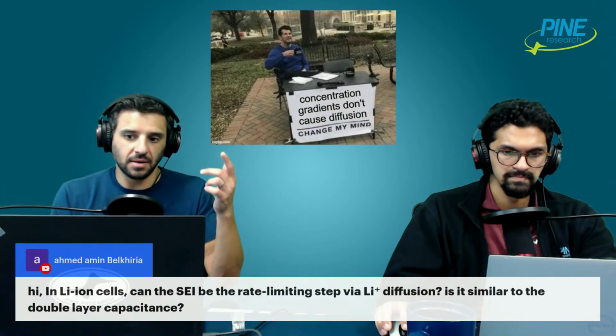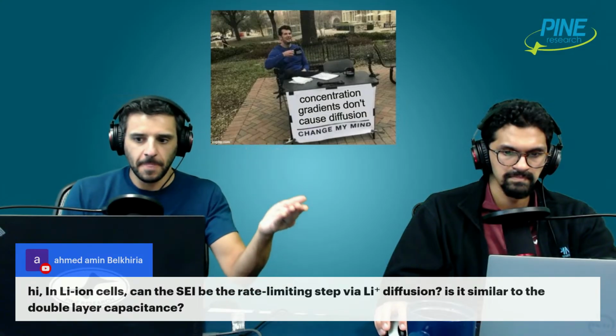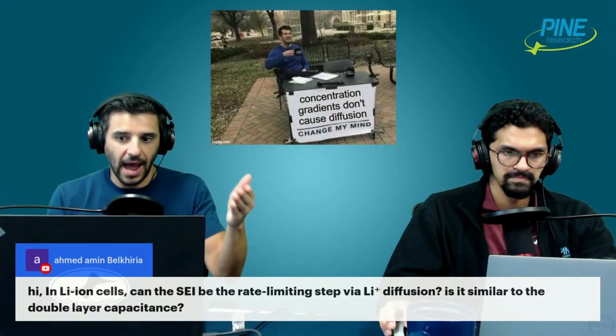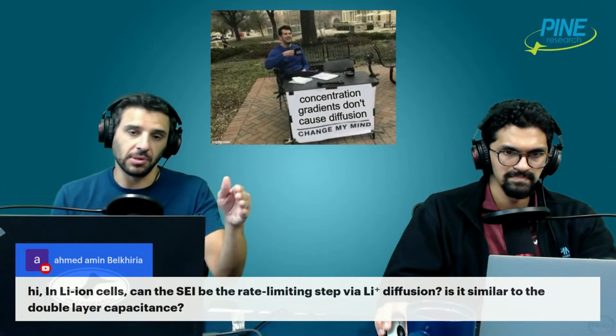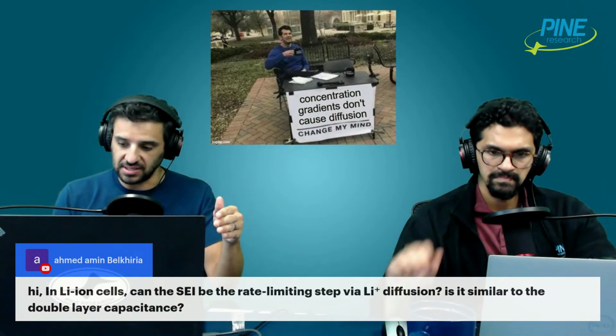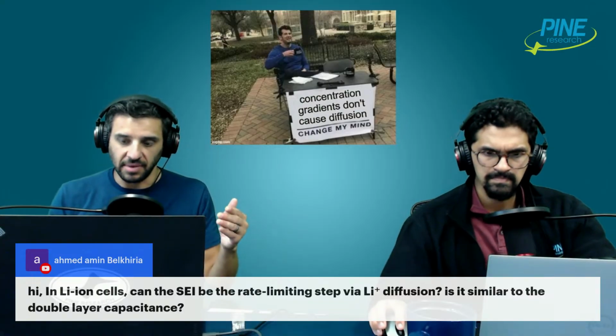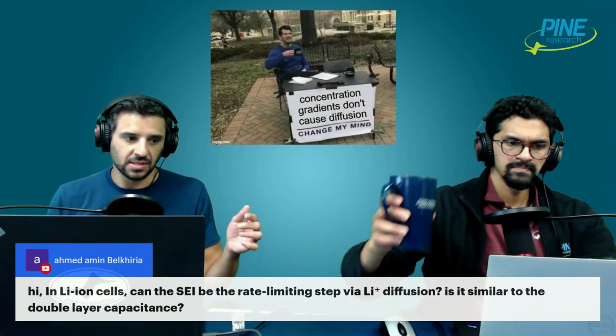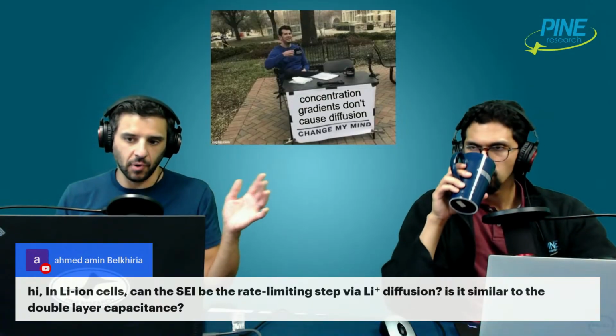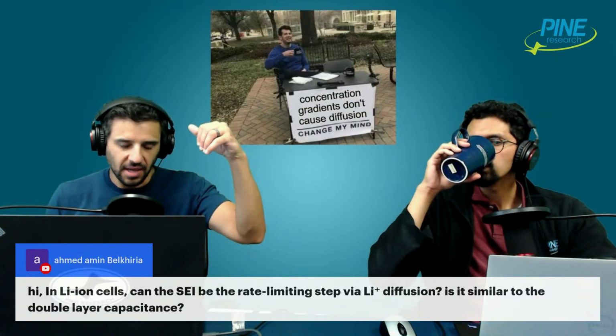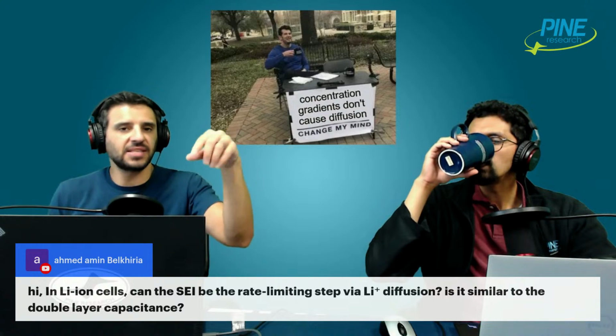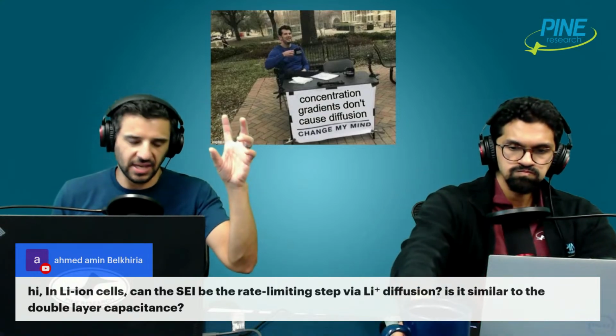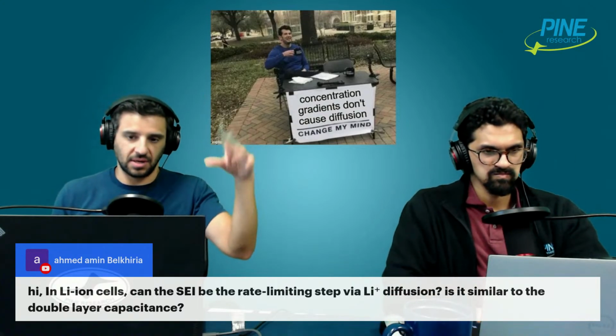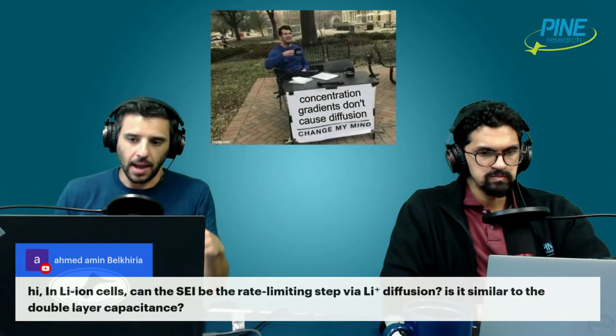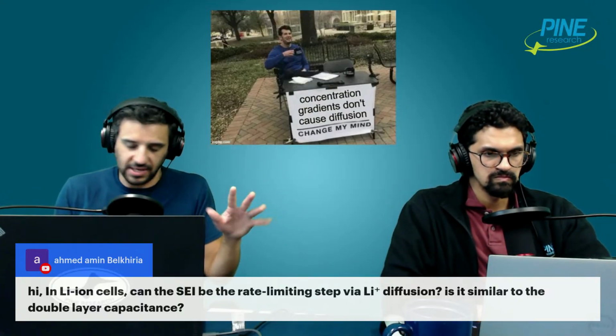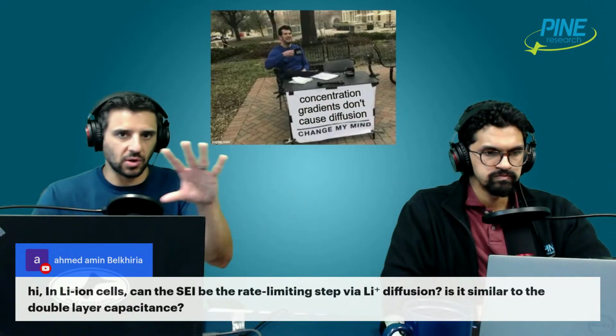So by that idea, no, it's not the rate limiting. It's similar to the double layer capacitance, although it is a separate process. But no, it's not rate limiting, because the SEI formation happens, and then there's no rate. There's other stuff that can happen with the SEI. It can thicken, it can collapse. Some of those secondary processes can occur, but I'm talking separate from that.